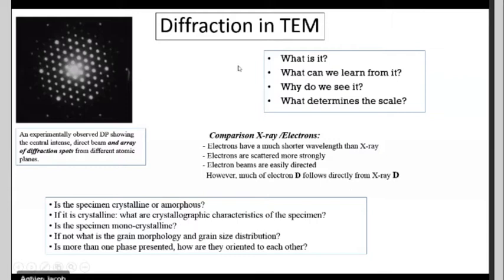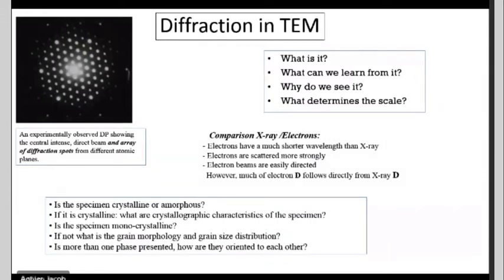In X-ray and neutron diffraction, the diffraction pattern forms on the same side as the diffraction surface. But in TEM electron diffraction, the electron is transmitted through the material and diffraction happens on the other side. We can extract crystallographic information — whether the sample is crystalline or amorphous, the grain morphology and grain size distribution, whether it is monocrystalline, and how many phases are present in the nano range.